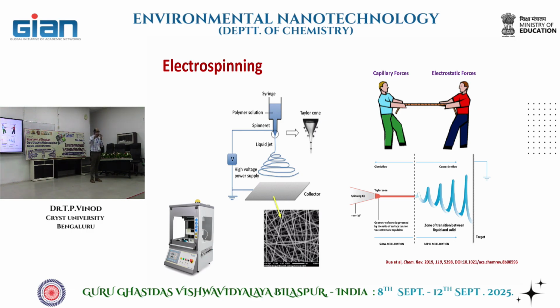From the Taylor cone, the jet is coming out. When the jet is coming out, the solvent in which the polymer is dissolved is getting evaporated. Then what's remaining? Solid polymer. In what form? Very thin, thread-like form. And that thread-like form is getting collected on the collector. Why? Because the collector is connected to earth. You have high charge, and then it wants to neutralize. That's why it will get deposited on the collector.